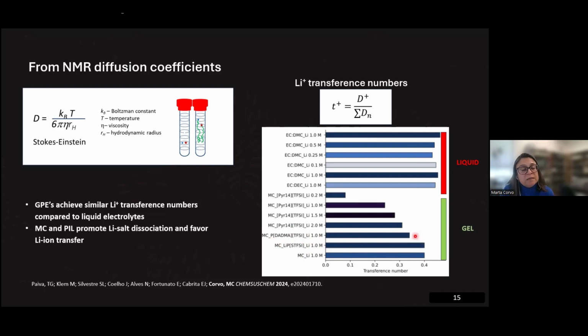This means that you can promote the dissociation of the lithium, so make it go around faster, just by changing the polymer matrix that you are using in your gel polymer electrolytes. Something else that is quite interesting is the behavior according to the amount of lithium, because when you get higher concentrations of lithium, it doesn't give higher transference numbers for the lithium in the respective gel polymer electrolytes. So you can even get higher transference numbers with a lower amount of lithium. This is quite interesting for us.